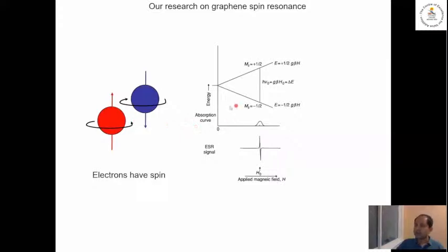And then it turns out if you put it in a magnetic field, then the two spin species develop different energies, and there's a gap between these electronic levels. And this gap increases linearly with the magnetic field. And further, this gap is in the energy range corresponding to, say, microwaves, right?